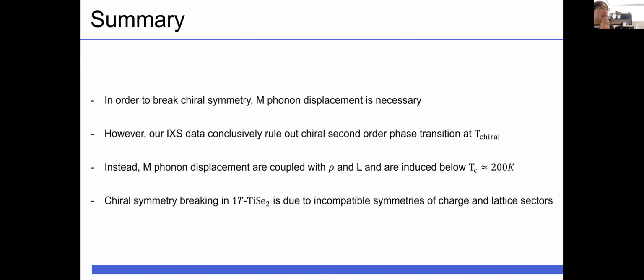Let me summarize my presentation. In order to break chiral symmetry, M phonon displacement is necessary. However, we cannot find a chiral second order phase transition below the critical temperature. So instead, M phonon displacements are induced below the critical temperature by coupling with rho and L. So in conclusion, chiral symmetry breaking in 1T titanium diselenide is due to incompatible symmetries of the charge and lattice sectors. And this is the end of my presentation, and thank you for listening.